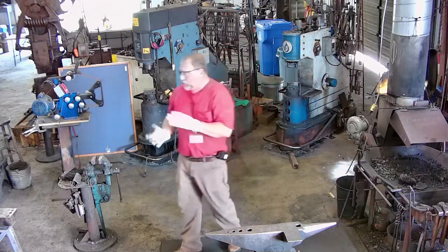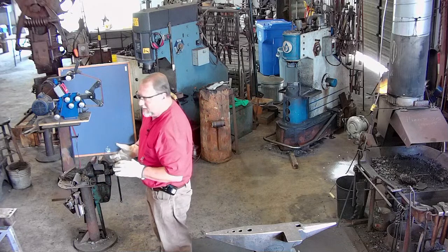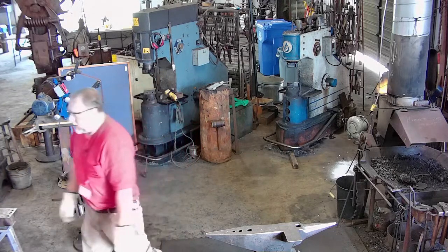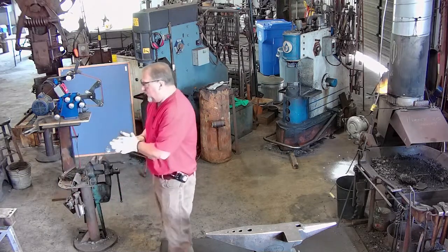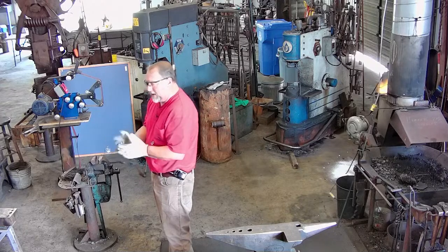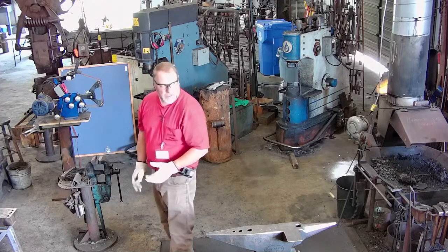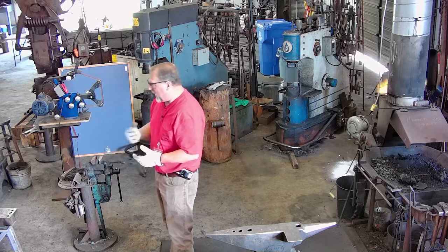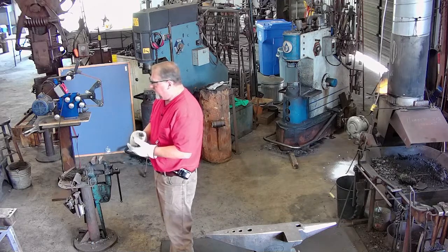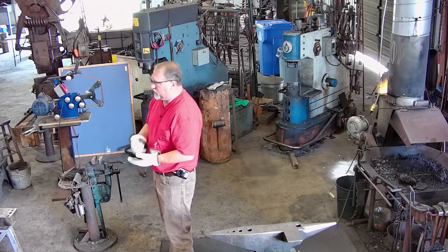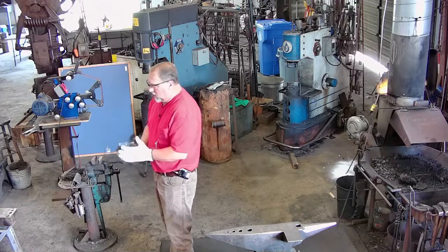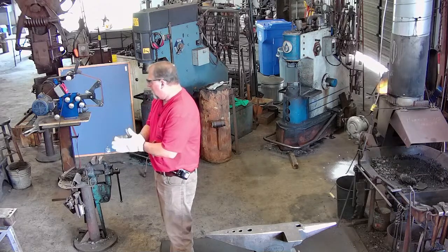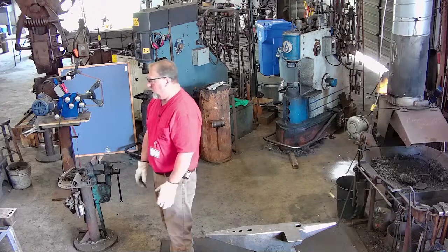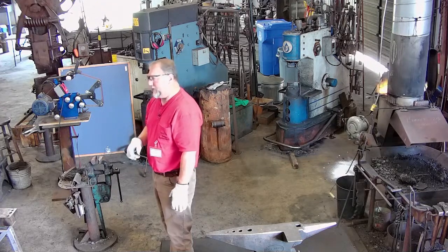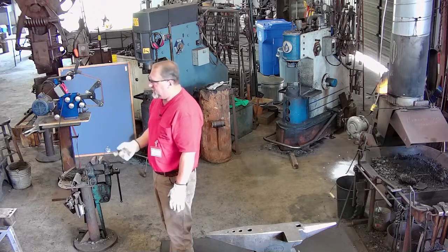And the main thing is, when you turn that billet on its side, you're creating a shearing force with that billet. So you have to be very conservative on how hard you hit it initially till you get it started reducing the size, which strengthens your weld. But if you start hitting it right away at a side angle, you can shear those layers apart. So you'll see I'm about as conservative doing it on the side initially as I was setting the welds.